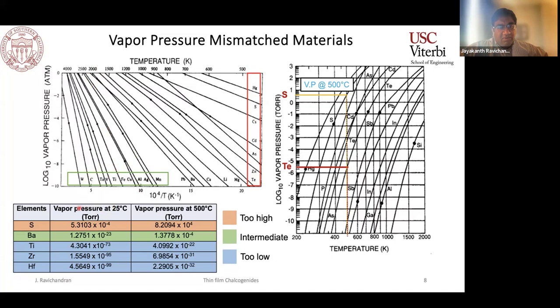To give you an idea, if you compare a select group of these elements that I showed in the previous slide, even at 500 degrees Celsius, you can see that the difference in the vapor pressure are dramatic, which means how do you ensure that you can control the flux of each of these species in a reasonable manner. At room temperature, it gets much, much worse, which means invariably you may have to evaporate or produce some of these vapors of the low vapor pressure materials and use some other techniques to do some level of matching of the vapor pressures to get your growth to work well.